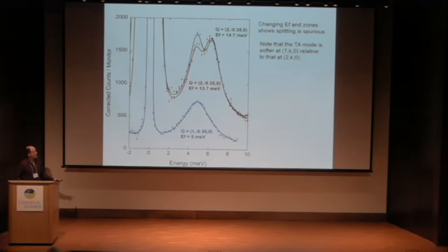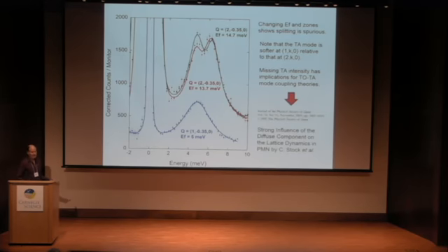Nonetheless, it happens. This was then the result of a paper by Chris Stock and Gen Shirane, who were discussing the waterfall and other various series of TO and TA mode coupling theories. I don't have time to go into that very deeply, but basically, this was evidence of coupling to the diffuse scattering, which is dynamic at high temperatures. That was shown using neutron spin echo. So that's actually kind of important. It shows that there is coupling, but it's to the diffuse scattering, not to the optic phonon.